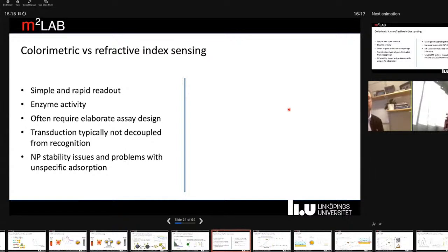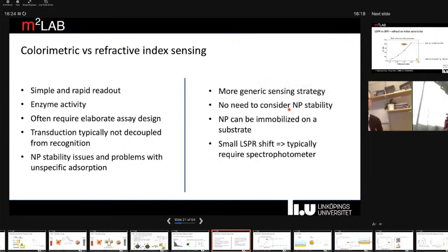And you also have some issues with nanoparticle stability, since colloids are not thermodynamically stable. They tend to aggregate over time or due to unspecific adsorption of proteins. So that's why we have also paid quite a lot of attention to refractive index sensing. Essentially approaching the same concept as used with SPR, just monitoring small changes in refractive index when biomolecules bind to the surface of nanoparticles. Because this is a more generic sensing strategy, you don't have to consider nanoparticle stability, and you can have the particles immobilized on the substrate. The downside is that the optical shifts here are very small, and you typically require a spectrophotometer of some sort.